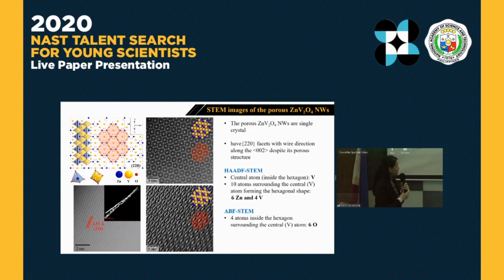Based on the STEM images, the surface of the nanomaterial has a 220 plane, which is indicated by the distance between the lattice fringes, approximately 2.97 angstroms, and that of the hexagonal pattern on both the HAADF and the ABF images. The hexagonal structure of both HAADF and ABF images corresponds to the 220 plane of the ZnV2O4.